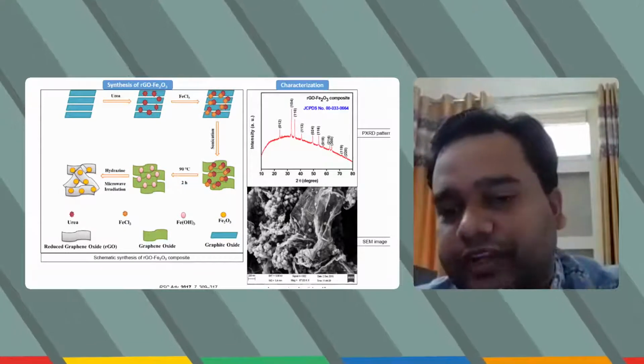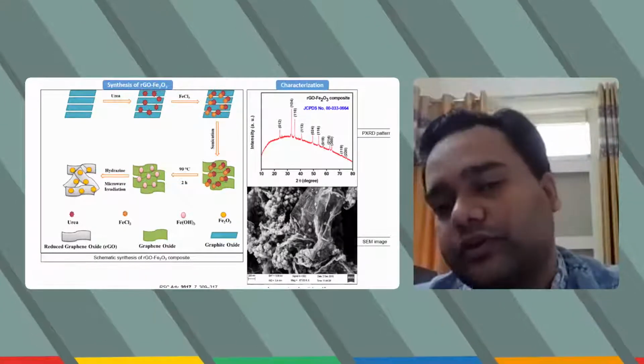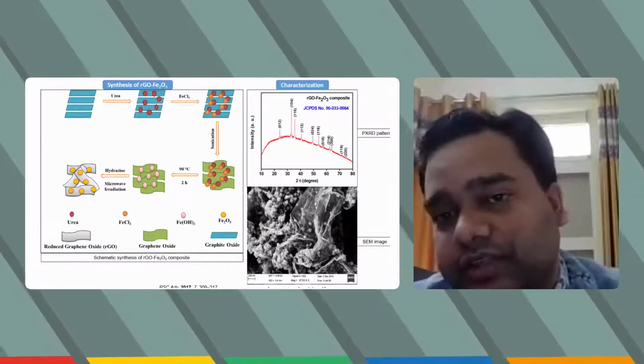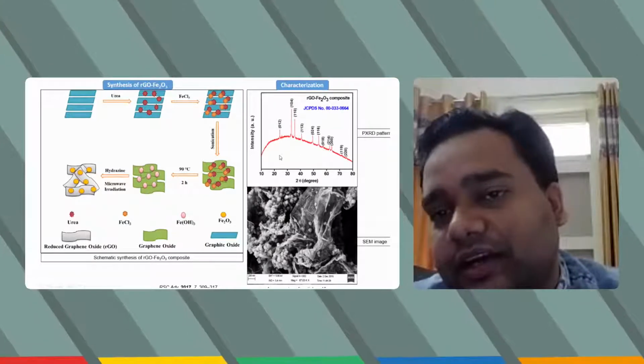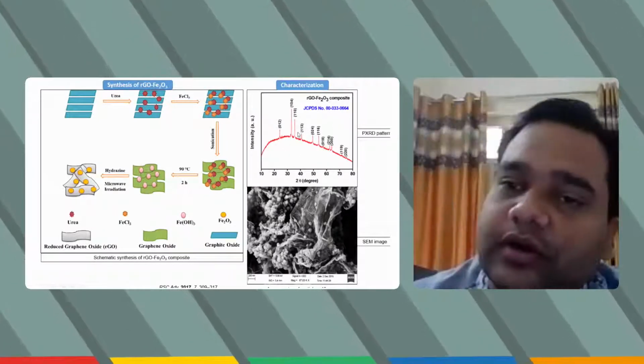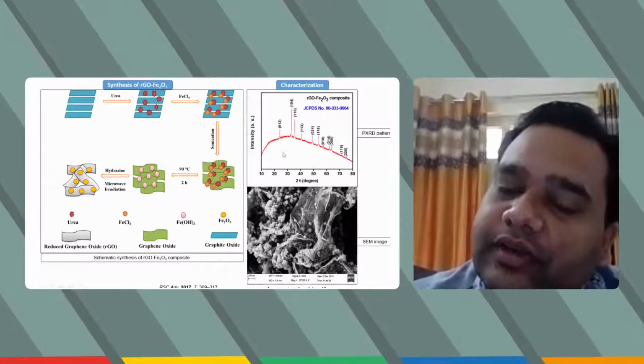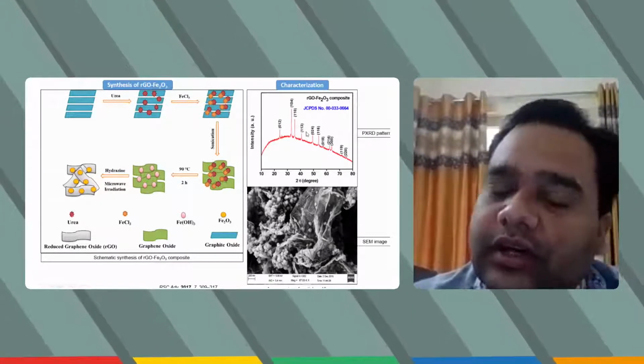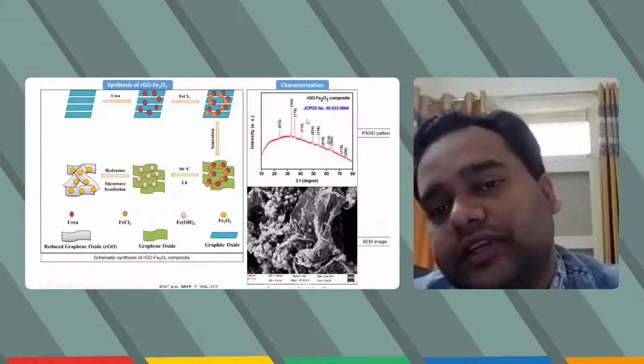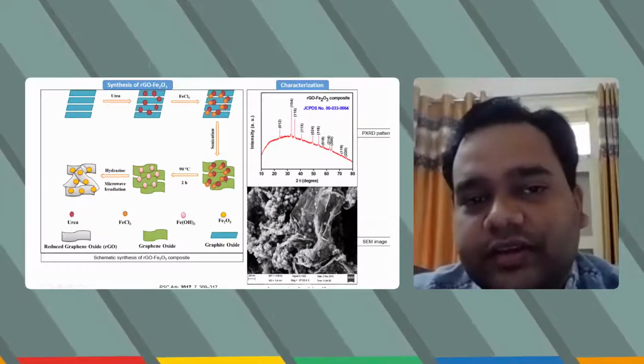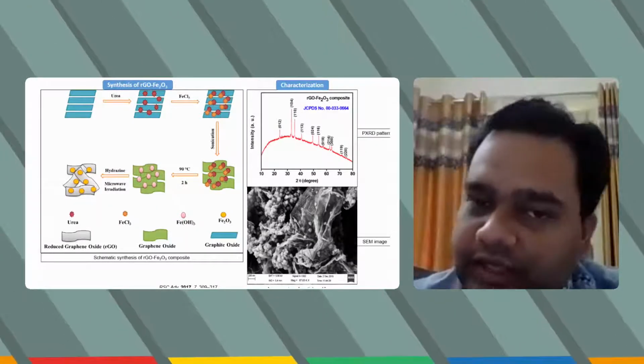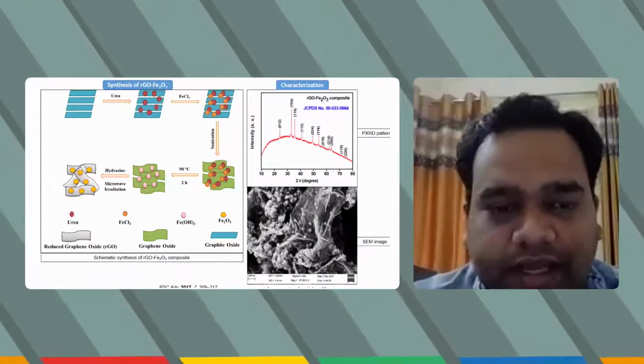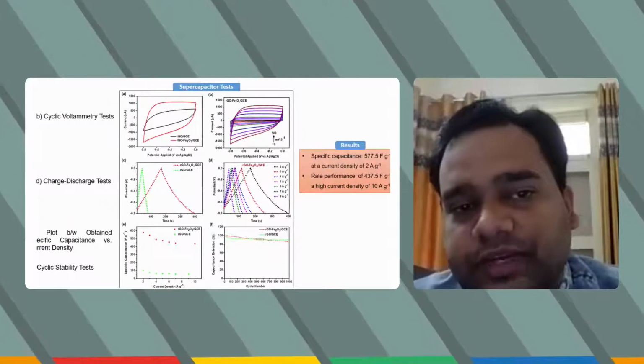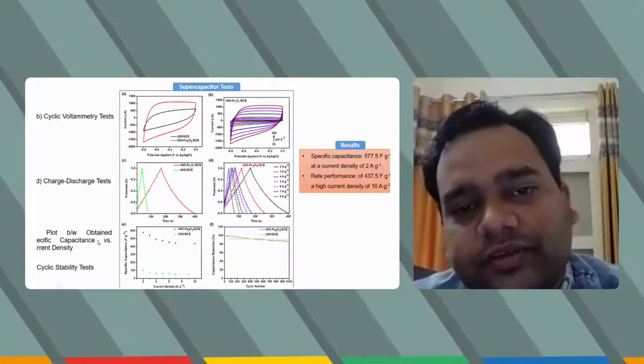So such kind of arrangement is quite beneficial for electrochemical applications. And this is PXRD, the powder X-ray diffraction technique. And this is a pattern where you can see all the peaks can be indexed with a standard JCPDS card. So these characterization techniques confirm that yes, composite formation has taken place, and now you can go for supercapacitor testing. So we can test it by various techniques.